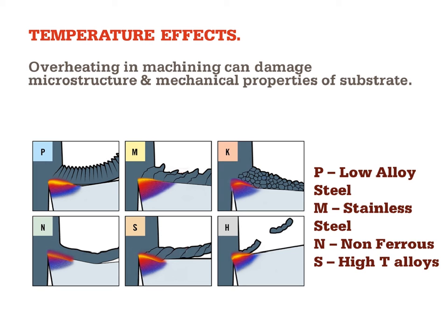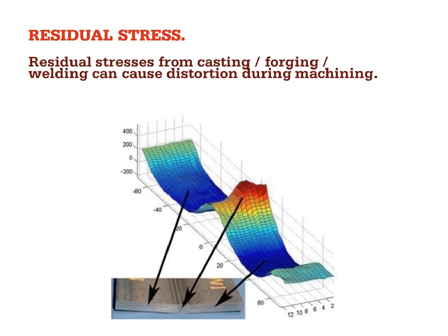And if you think back to the heat treatment, we are now taking the material into a high temperature region. We're going to modify its mechanical properties, which we do not necessarily want to do. We will also have, in the remaining material after the machining has been carried out, residual plastic stresses embedded in the product, which can lead to mechanical distortion, dimensional distortion after machining. So we have to understand the machining process and the limitations imposed by temperature and plastic strain, the limitations that are imposed on the machining rate.